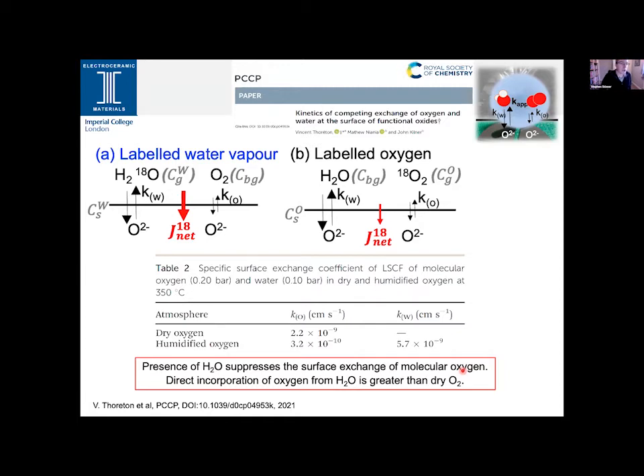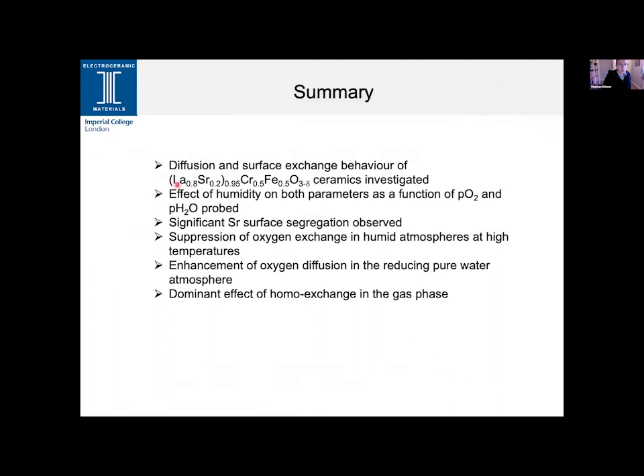I note that I'm getting towards the end of my time, so I'll finish off with my summary. We've investigated diffusion and surface exchange behavior of our lanthanum chromate ceramics, probing the humidity on both the parameters as a function of PO2 and pH2O. We can see significant strontium surface segregation, not necessarily surprising. We do get suppression of oxygen exchange at high temperature in humid atmosphere, enhancement of oxygen diffusion in the reducing pure water atmosphere, and a dominant effect of the homo-exchange in the gas phase, affecting those surface exchange parameters. That effectively leads to the conclusion that a significant amount more work is required to fully understand the exchange behavior in these mixed gas atmospheres in these perovskite phases.